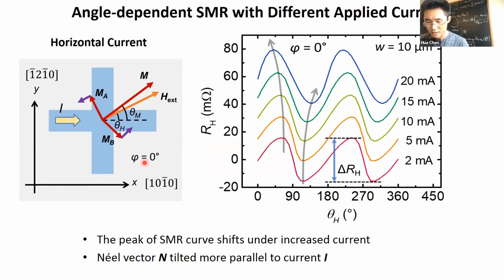The first is, since hematite is a weak ferromagnet, from the symmetry point of view, it can pretty much be understood as a ferromagnet, except for the very strong easy plane anisotropy. In the current setup, it seems hard to make use of the damping-like torque because it tries to rotate the moment out of the easy plane. Yes. So have you considered growing the sample with the easy plane perpendicular to the Hall bar plane?